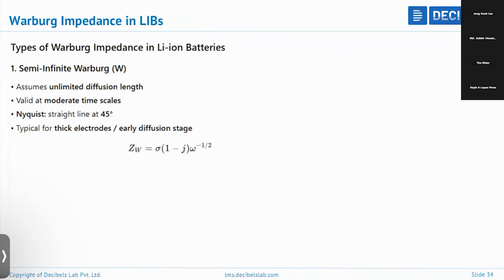And the Warburg, actually, we have three types. One is the semi-infinite Warburg. It assumes unlimited diffusion length, so it is valid at moderate time scales. It is actually when we get a straight line at 45 degrees in the lower frequency region. So typically it is for thick electrodes. This is the impedance equation corresponding to that.